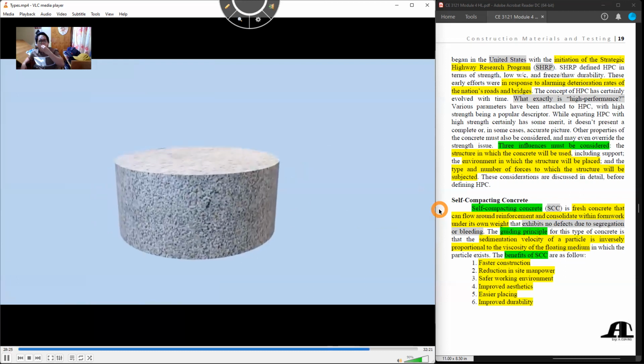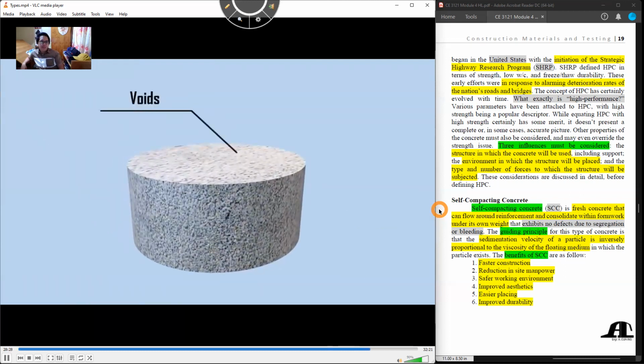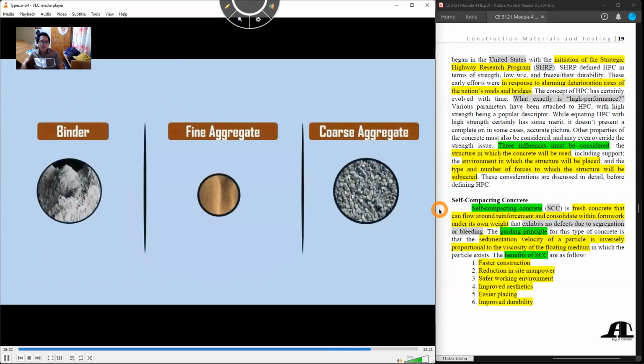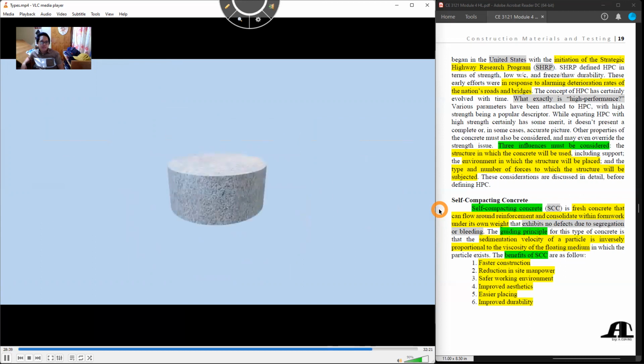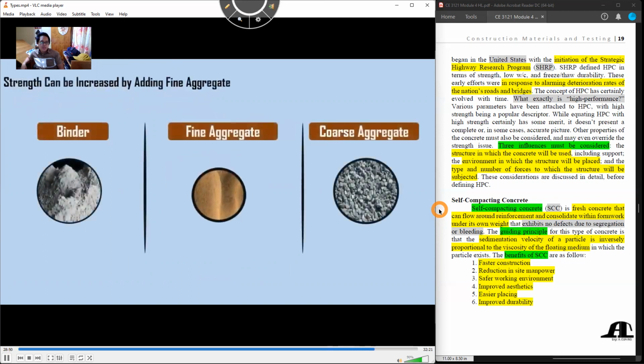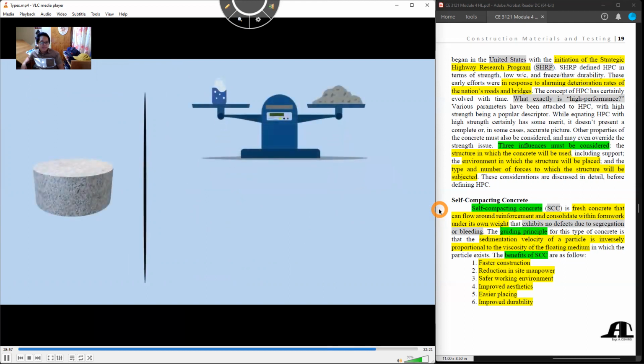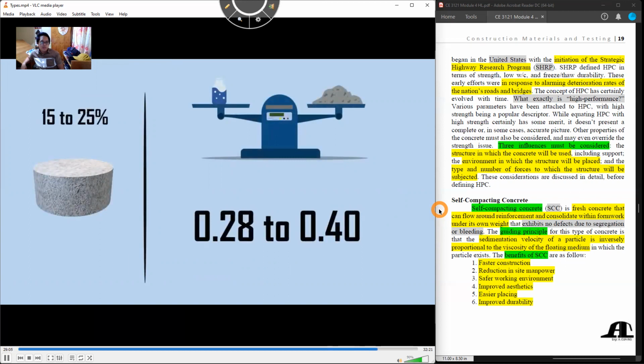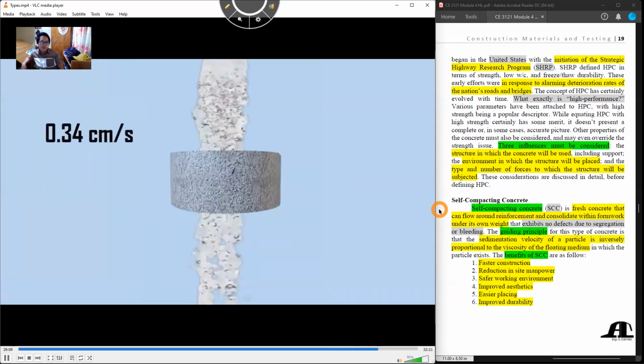The high porosity is attained by a highly interconnected void content. Pervious concrete consists of cement, coarse aggregate, and water with little to no fine aggregates. The high porosity reduces strength compared to conventional concrete mixtures. However, the strength can be increased by adding the required fine aggregates. The mixture generally prefers a water-cement ratio of 0.28 to 0.40 with a void content of 15 to 25%. The average flow rates for water through pervious concrete are typically around 0.34 centimeters per second.